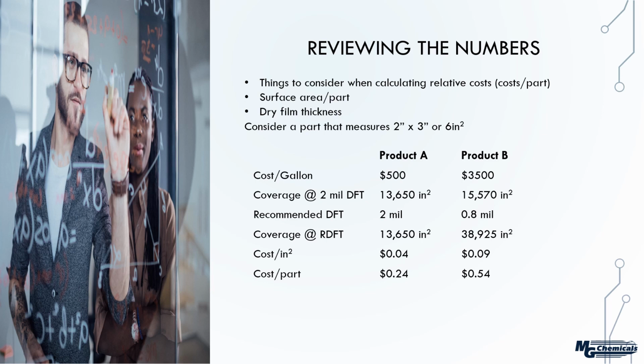So when we look at the coverage in terms of what's recommended, now we're almost at 39,000 square inches compared to 13,650 in the first example. The cost per square inch is now 9 cents, and cost per part, it comes in at just 54 cents per part. So you can see how we started at 7 times the cost in terms of the volume, but when we really take into account the surface area, the efficiencies, that sort of thing, we narrow the gap considerably, where it's just a little over 2 times the cost in terms of per part.